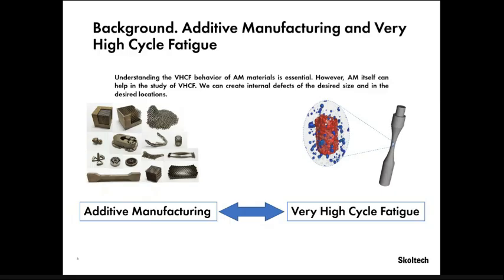First of all, studying the very high cycle fatigue of additively manufactured materials is important, since they are already implemented in many industries, and the parts can potentially work in harsh loading conditions, such as this high number of cycles. But at the same time, additive manufacturing allows us to print small structures, like small artificial defects of desired size and position. Such artificial defects can be used in the study of very high cycle fatigue, and not only that, they can be useful in many cases. So in our work here, we study artificial defects and their effect on very high cycle fatigue.